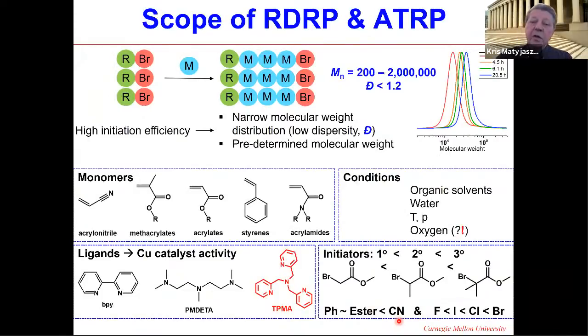So what is the typical scope of ATRP and some other controlled radical polymerizations? We can make, as Craig showed, oligomers. Degrees of polymerization can be sometimes 2 or 3 or 4 or 5, and typically we can reach molar masses even exceeding 1 million, with dispersities, as Craig said, 1.2, sometimes 1.1, or sometimes less. So very high uniformity of these chains. In ATRP, we need monomers which would typically stabilize radicals by either a triple bond or double bond, like methacrylates or acrylates or acrylamides, or also you can have benzylic structures.